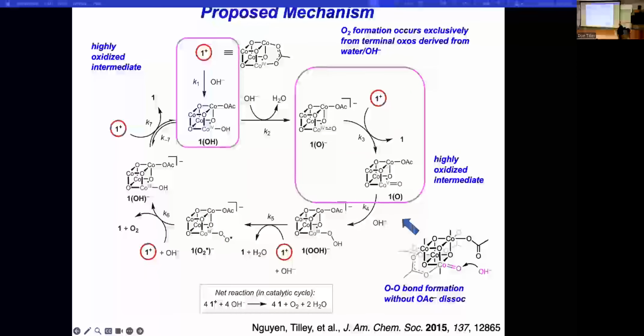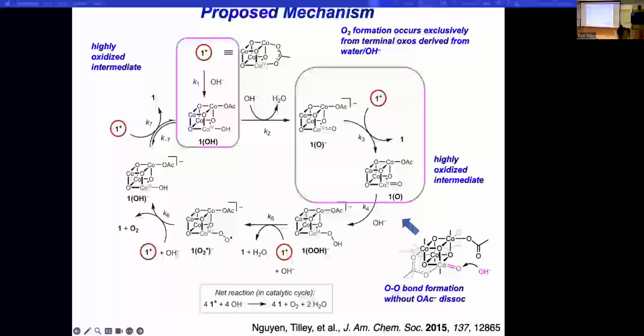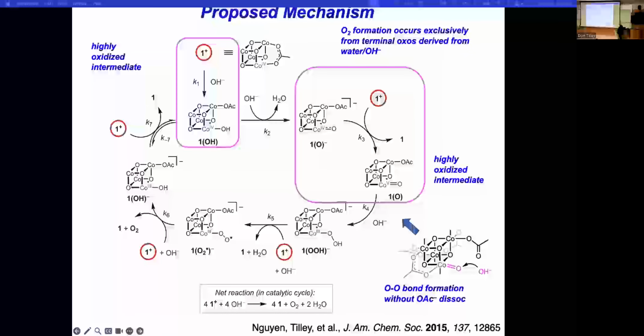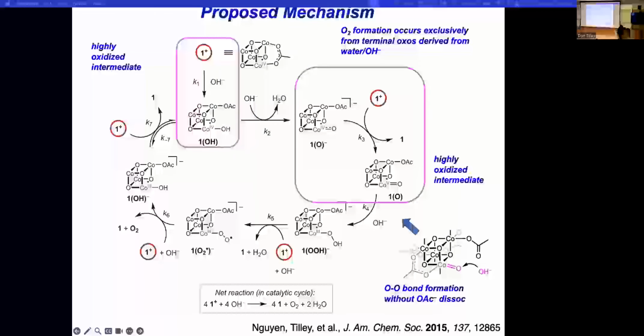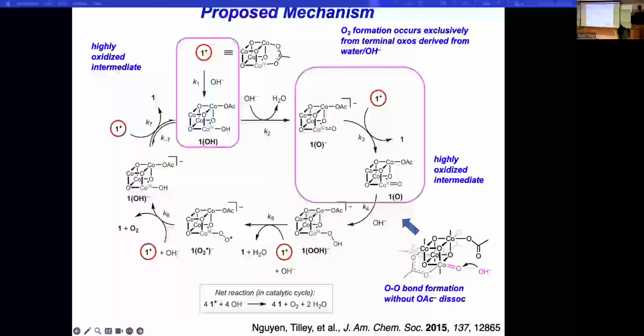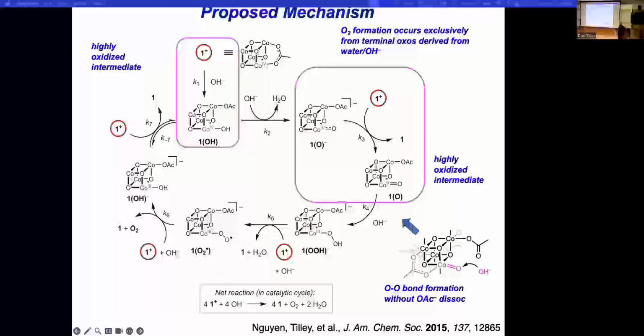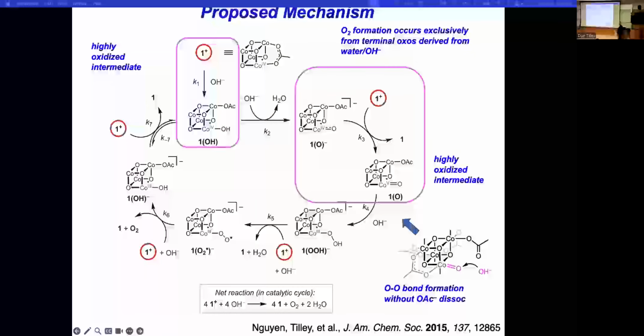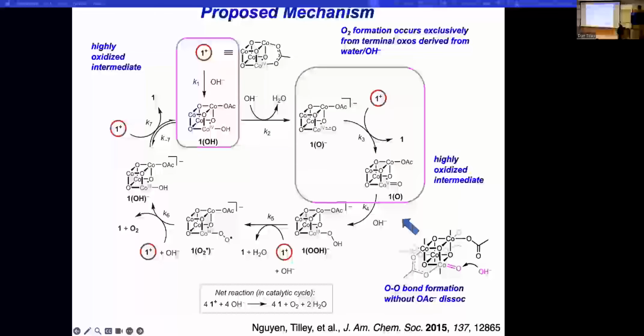But in fact, we're quite convinced that that second order term is due to this disproportionation reaction, which puts another hole on a cubane. Now that is the only evidence we had for suggesting and thinking about two holes on a cubane and there being an oxo ligand there, and that means cobalt 5. So at this point, and even still, cobalt 4 is very elusive synthetically, right? That's something that inorganic chemists try hard to make. So cobalt 5 seems a little bit more of a stretch, but we think that this is real. Something formally with that oxidation state.